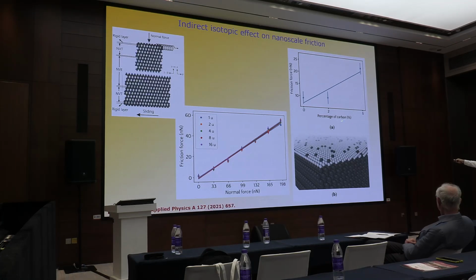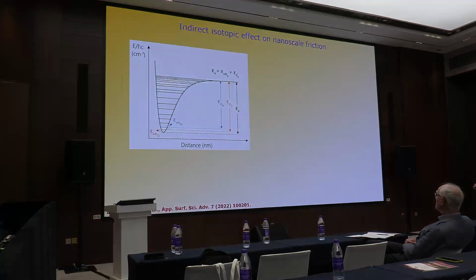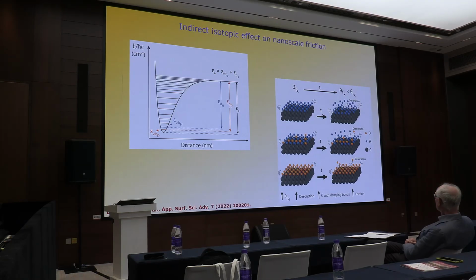The friction force depends on the coverage. When we have more carbon exposed, the simulation says you have more friction. More carbon, more friction. What does it mean? You have desorption. If you have desorption of hydrogen or deuterium, you have a dangling bond of carbon and increased friction. We published another work in parallel with this, where we could explain that the isotopic effect is not phonon dissipation. The isotopic effect is desorption.